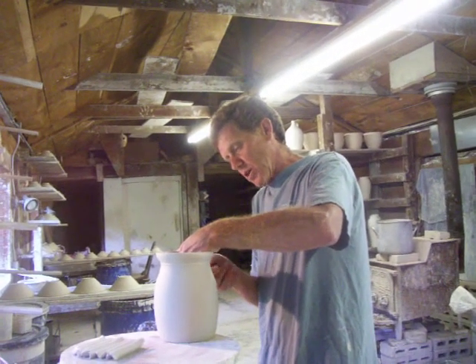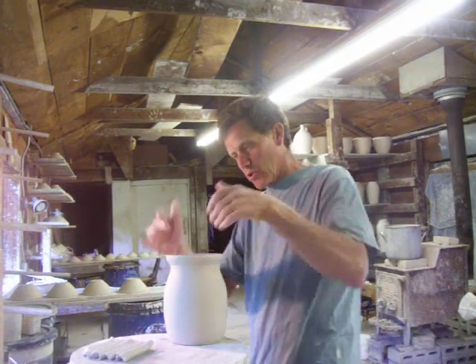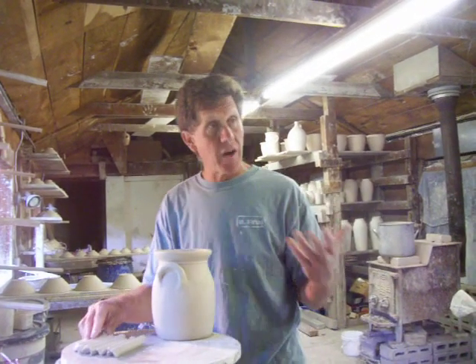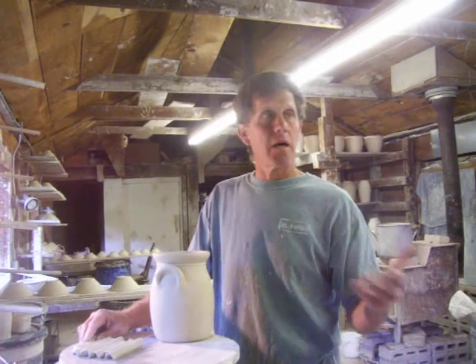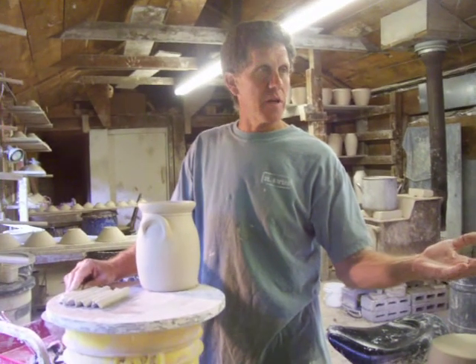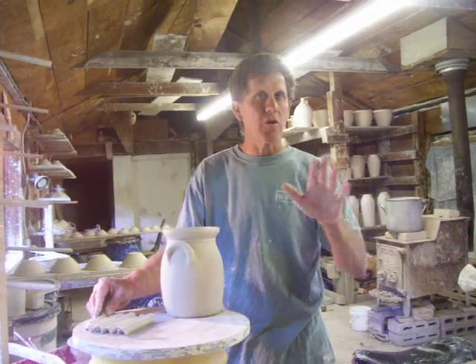Flames in a wood kiln are continually oxidizing and reducing flames, and the chemical reactions which are taking place in the pot are very sensitive to those kinds of environments. When you're talking about oxides, calcium oxide, potassium oxide, that's what pots and glass are composed of. Well, they can be reduced to their base metal state or oxidized, which means they get another oxygen, and it's a totally different look.